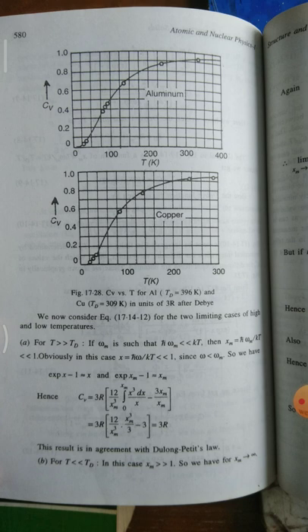We now consider the equation for the two limiting cases of high and low temperature. For T much greater than TD, if omega M is such that h-cut omega M is much less than KT, then xm is equal to h-cut omega M by KT, much less than 1. Obviously in this case x equal to h-cut omega by KT is much less than 1, since omega is less than omega M. So we have e^x minus 1 approximately x, and e^xm minus 1 approximately xm. Cv is equal to 3R [12 by xm cube integration 0 to xm of x cube dx by x minus 3 xm by xm], which is 3R [12 by xm cube into xm cube by 3 minus 3], which is equal to 3R.